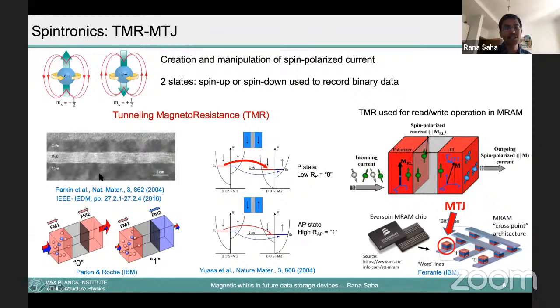Electrons can basically tunnel. It's a quantum mechanical tunnel. Electrons can tunnel from one layer to the other layer. And this tunneling process again depends on the state of magnetization of these two layers. For example, if you see here, if these two layers are red colored, if you think both are ferromagnetic layers, the electron can tunnel easily from one state to the other because of the same spin polarization, because both are up spin, let us assume. As you can see here, it can easily tunnel from up to up.